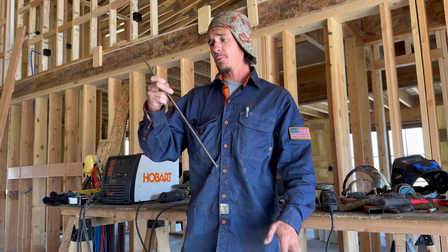Now this is a really good trick if you're new to the game and you're not really confident with your open root skills, because an open root weld can be kind of intimidating. So this is a good way to get around that. If you can access the back side of whatever you're welding, you can just clamp one of these copper backing bars on there and get a fully penetrating, nice looking through and through weld pretty easily.